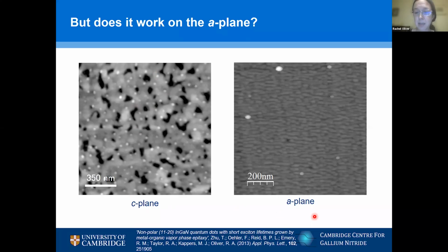If we carry out the same process under actually really similar conditions on the A-plane, the morphology isn't the same, but it has some broad scale similarities. We've still got our little tiny metallic droplets. Here they are sparse, but that's not a bad thing when you're making single photon sources. It allows you to separate out individual dots. And we've got a quantum well layer that in this case is rather more decomposed into nanoscale areas, but is still a quantum well layer with holes in.